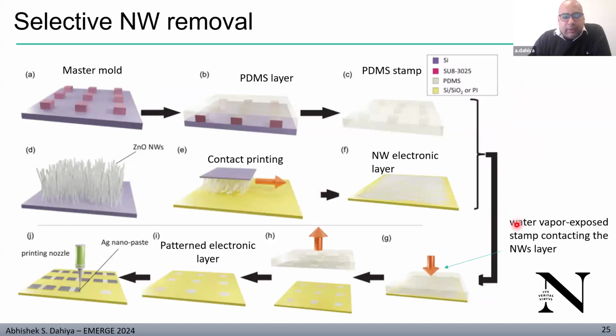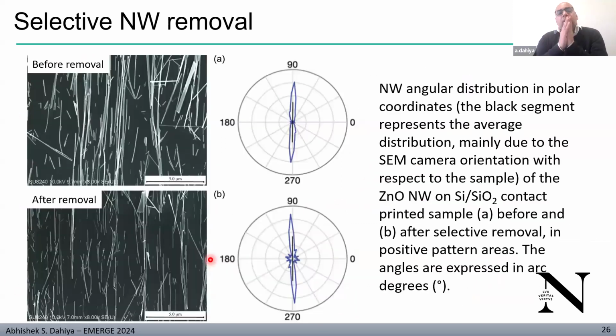These are the process steps for this. We have a mold and the master template, and then you make your PDMS stamp from this. You have these printed wires, you contact, you make electronic layer, and you remove it. In terms of results, this is the SEM image showing before and after removal of the wires, showing that the alignment of wires has not changed.